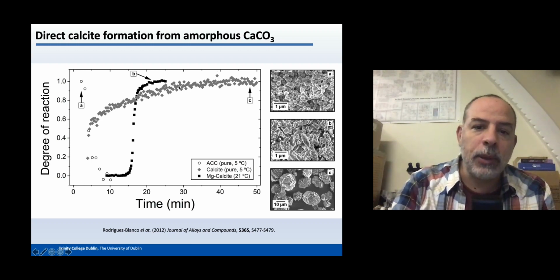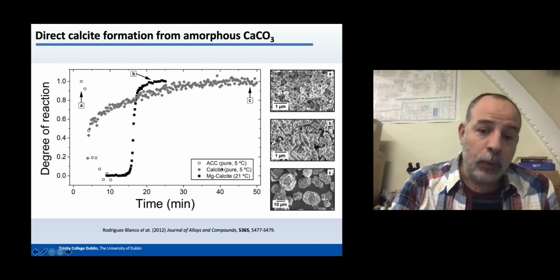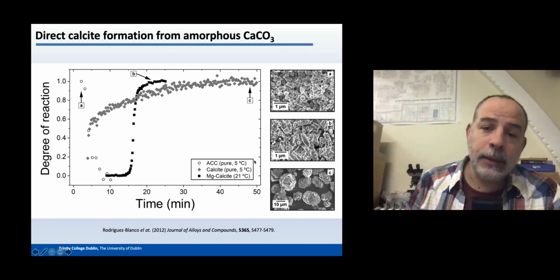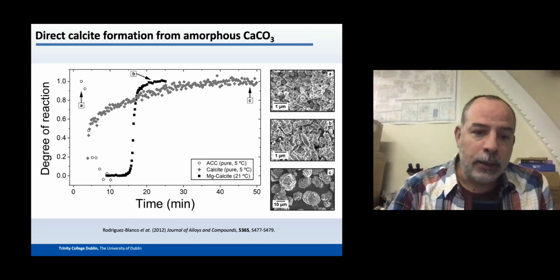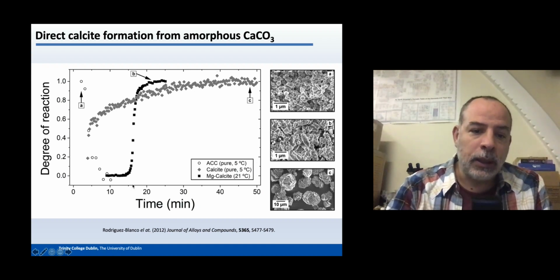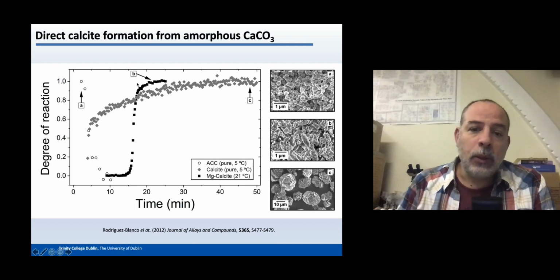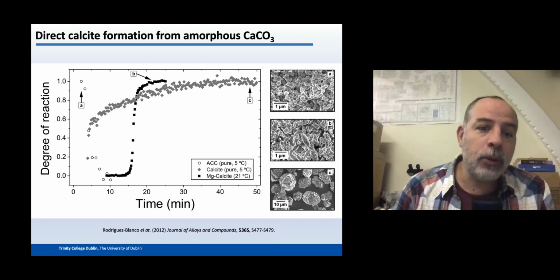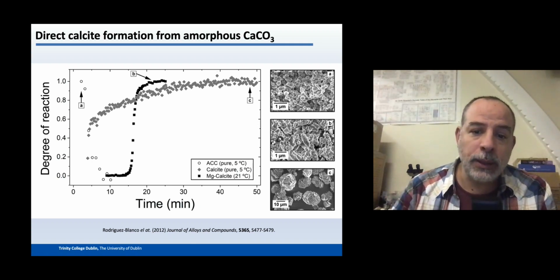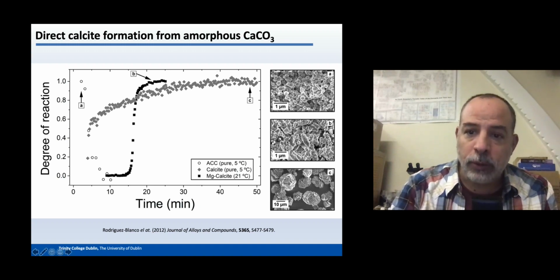You see that the whole process is gone in less than 1 hour, and we are using low temperatures to decrease the kinetics of the reaction. And here magnesium calcite forms in less than 20 minutes at 21 degrees C. It would be very difficult to follow what is happening if we were not using synchrotron-based techniques. So this is what you see, amorphous calcium carbonate forming calcite or magnesium calcite.